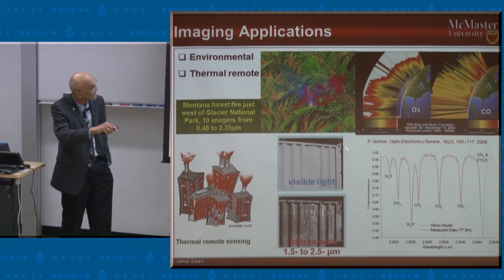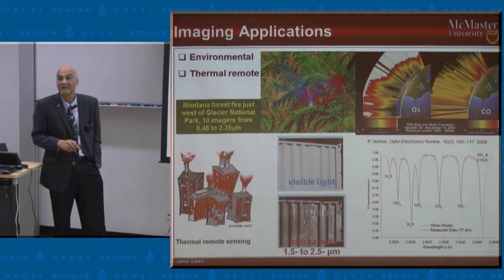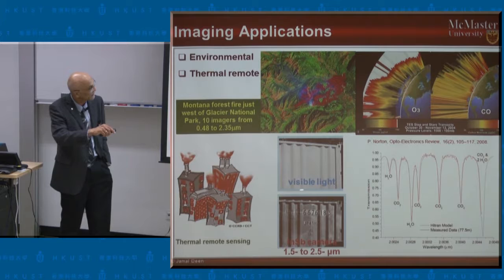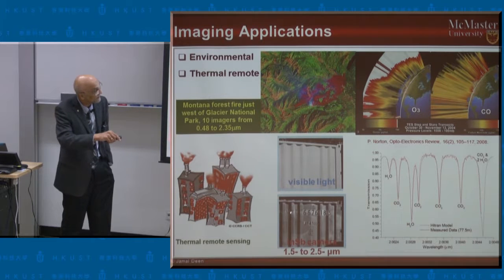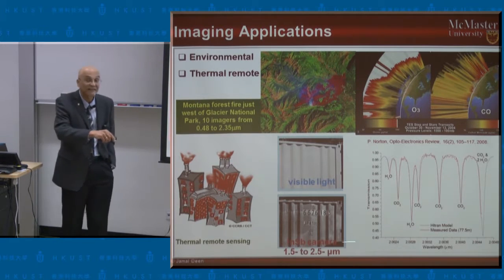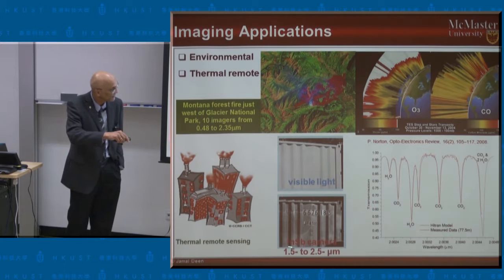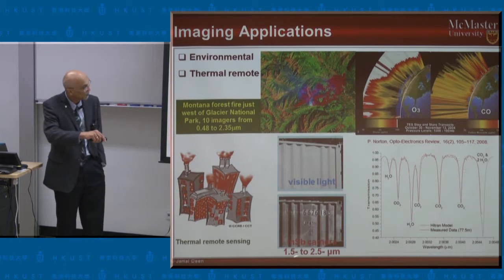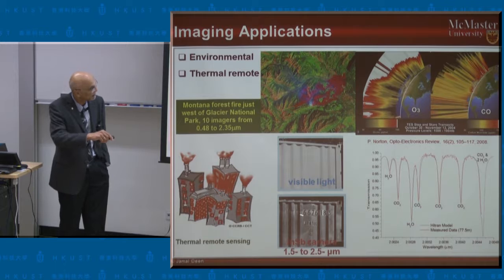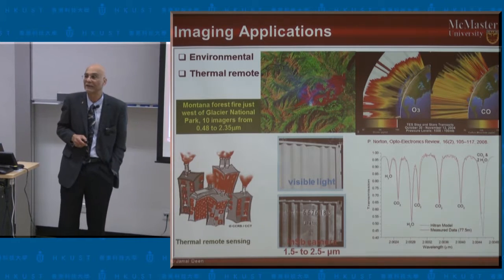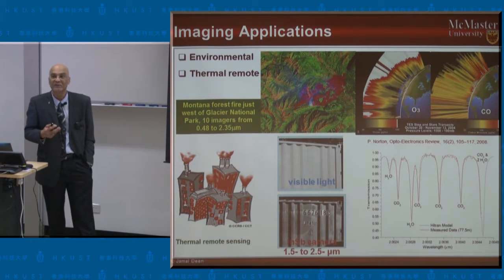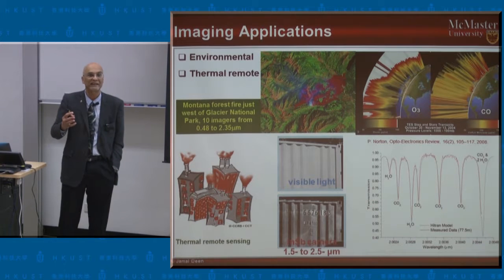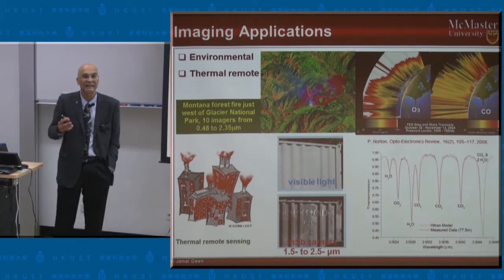So this is an example of a container in which we've taken an image using visible light, and we cannot see the identification mark. However, if we extend the range of wavelength, and this is using an indium antimonide camera, from 1.5 micron to 2.5 micron, we can clearly see the identification mark. So these types of images really allow us to extend our ability to see as humans.